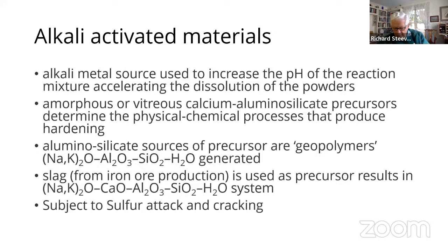And if you get sulfur into the voids in the concrete or in the cement, then the crystal structure changes and those crystals get bigger, and that causes the cracking. So again, this is something in this formulation that tries to avoid the voids from forming and prevent this conversion of these crystals to larger crystal structure.